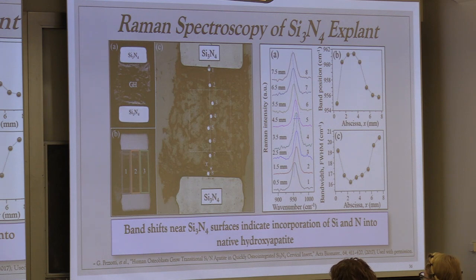So it says that what's happening is that silicon nitride is actually donating some of its ions, in this case silicon and nitrogen, and they're basically endocytotically taken up by the osteoblasts and incorporated into hydroxyapatite. Now, it's well known that silica as a material is a very osteopromotive material, but these are among the first studies that show that silicon nitride is as well.